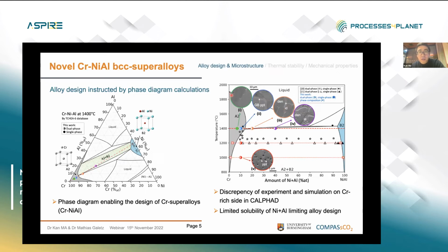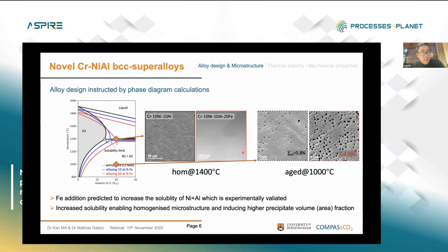And what's more, the CALPHAD database of the chromium-rich area in fact needs further investigation because it overestimates the single phase area. That means we cannot add as much nickel and aluminum as predicted. It limits the volume fraction of the precipitate that we can create in the material, so it limits the strengthening. So the first step is to seek a way to increase the solubility of nickel and aluminum.